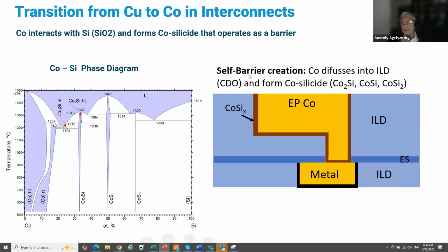Why doesn't cobalt need a barrier? Because, you can see on this phase diagram, a lot of intermediate compounds of cobalt and silicon, cobalt silicide. And what happens, cobalt diffuses into silicon oxide, interacts with silicon, and creates cobalt silicide. First of all, cobalt silicide has very high density, and they have very good conductivity. Therefore, it's like a self-barrier. Of course, the process is not so trivial as I explained, but I'm talking about principles.